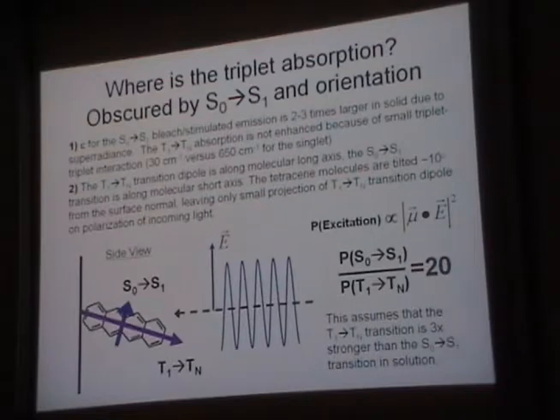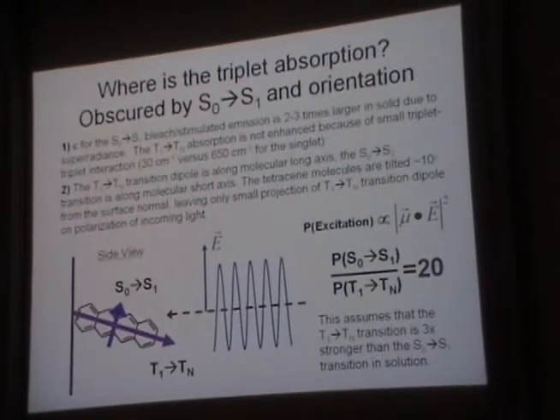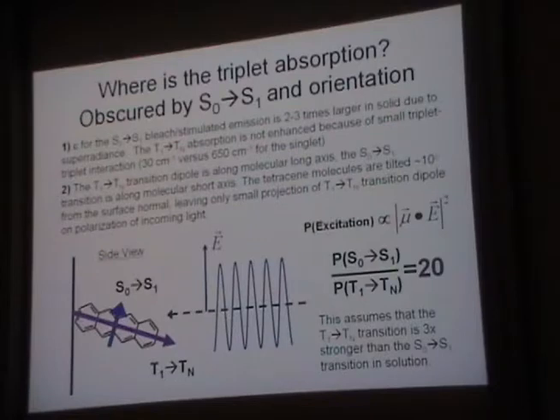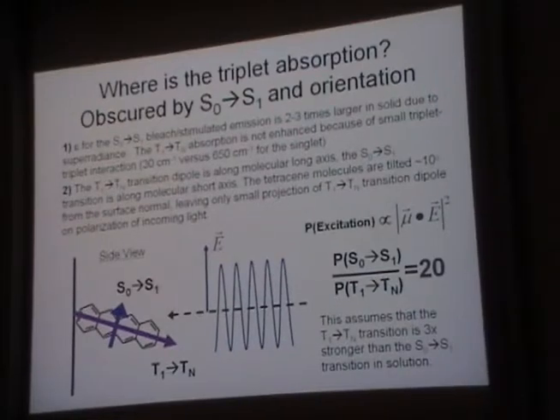absorption experiments. All right, and coming in at an angle does not help very much, although it does help, and we didn't do that experiment. It was done in Pentacene, and to be honest, the amplitude of the triplet that they see in Pentacene is exactly what our calculations say it should be if we have 100% triplet. But this is not very satisfying, right? I'm arguing, is it evidence of absence is not absence of evidence? Something like that? Or it's vice versa. My Dick Cheney quotes are eluding me. This is an excuse for why we don't see the triplets. But you could say, well, you don't see the triplets, but it still could be that the triplets aren't there.